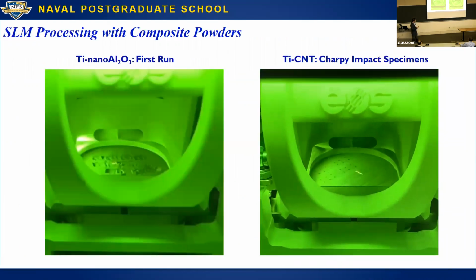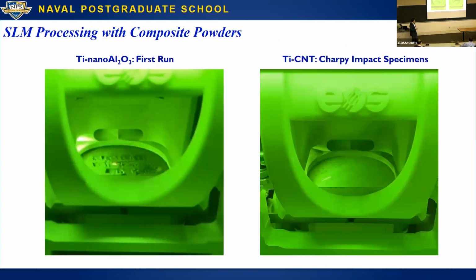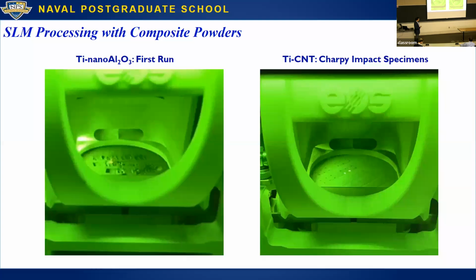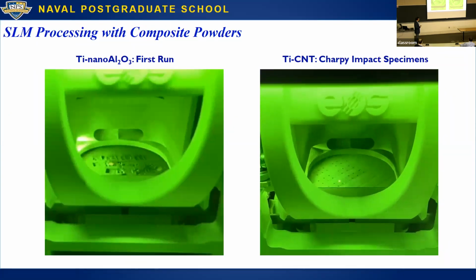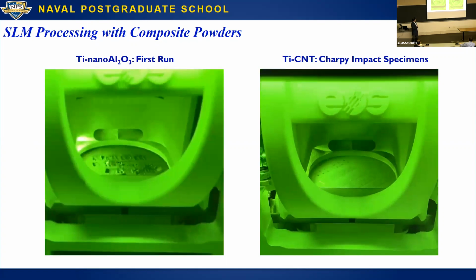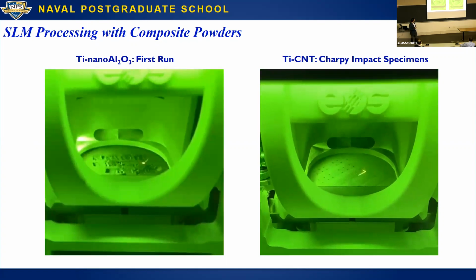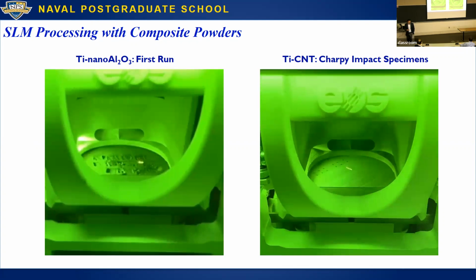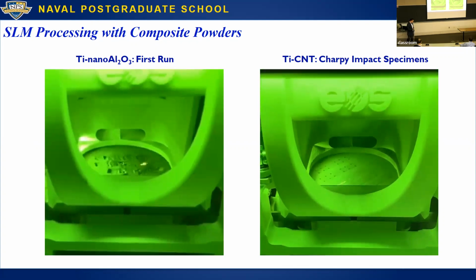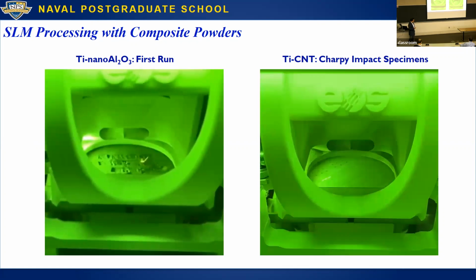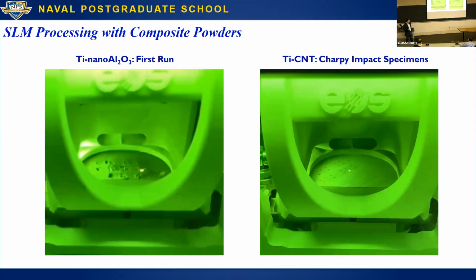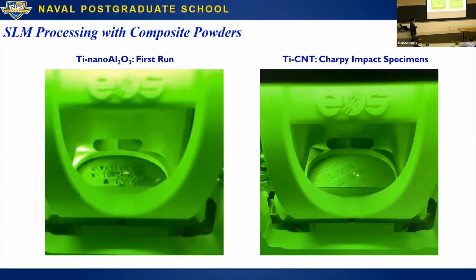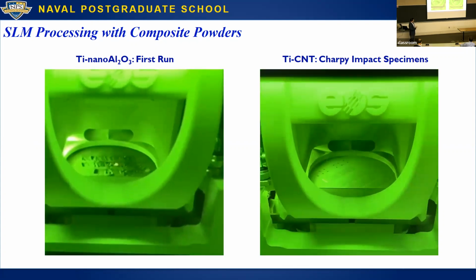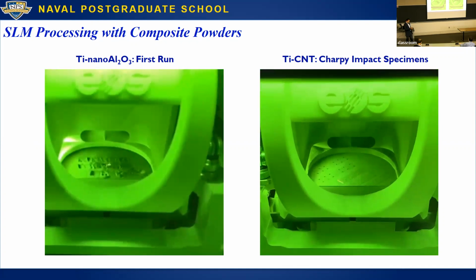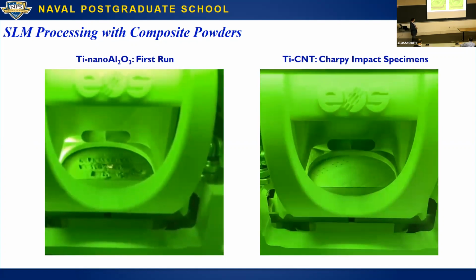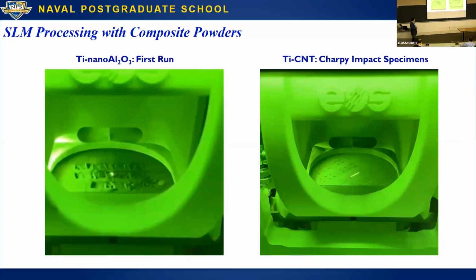So the 3D printing itself comes with a lot of challenges when we start adding these different composite phases. So at left here, you actually see one of our earlier runs with the titanium powder with nano aluminum oxide. This was essentially our very first run. No optimization. We were essentially using the same parameters as Ti-64, and you see a lot of issues here. One, the powder bed was actually not spreading very nicely. The nanoparticles were causing some roughness, and essentially the powders were sticking together more.